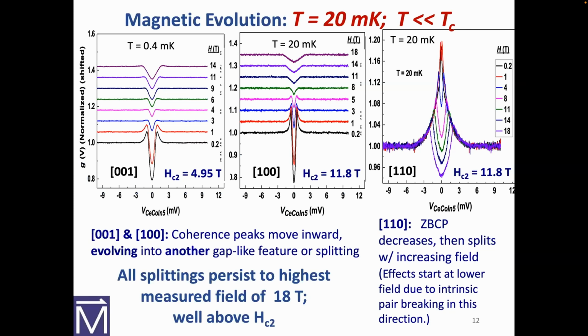Now we're going to look at something that I found really interesting, and that's the magnetic evolution. I'm not going to talk about the nodal direction on the right, except that in zero field, in very little applied field, it splits already, which you expect for the nodal direction. So let's look at the first two. They're low temperature. The C-axis one is 0.4 millikelvin, and the next one in the A direction is 20 millikelvin. And we see something really interesting here.